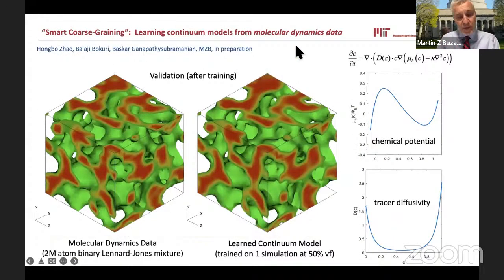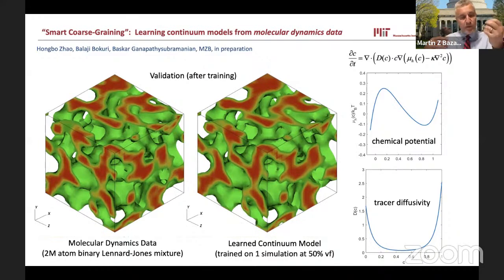Now, before I show you the battery problem, let me just impress upon you the generality of this method, which I frankly find really amazing. So here's an example we still have not published yet, but we're working on it, which is to learn a similar phase separating model. In fact, it's the very same Cahn-Hilliard equation in a totally different situation of molecular dynamics simulation of a binary Lennard-Jones mixture. This is a simple MD simulation of 2 million atoms in a periodic unit cell in 3 dimensions. The 2 million atoms are broken into 50% of one type and 50% of another type. So it's like a black and white, or A and B.